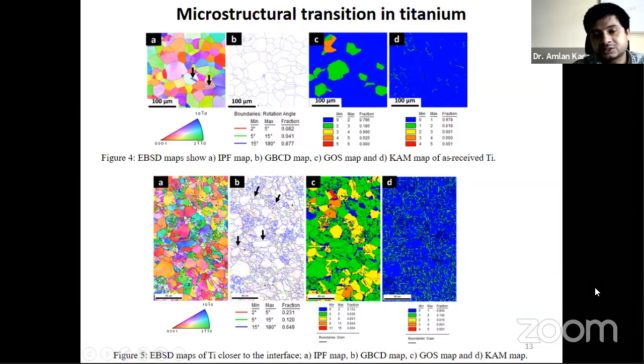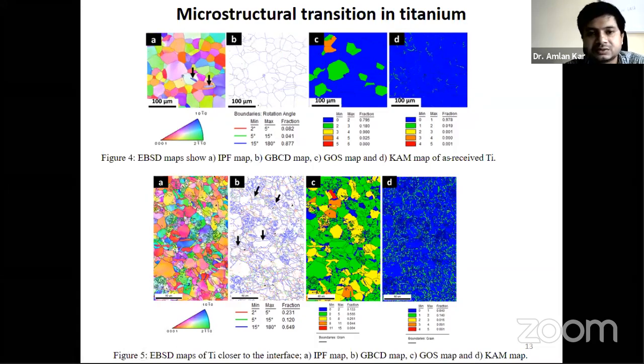From there we can understand that titanium has an HCP crystal structure, which has only three slip systems, of which two are independent, and titanium has a low thermal conductivity. The deformation leads to temperature evolution that could not transfer from the deforming locations to the surrounding locations under high strain deformation conditions. And titanium could not accommodate a large amount of strain as well.